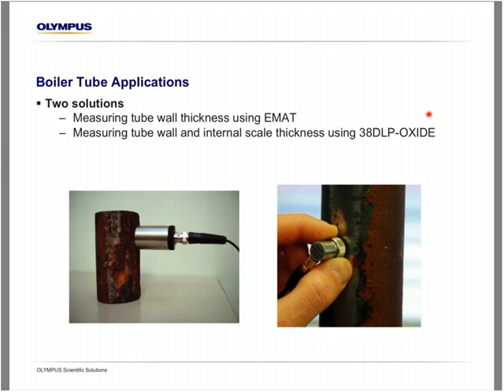So you can see that on the left here. This requires that external scale, and it's really designed to be an initial screening tool to determine if the boiler tube wall thickness is still within spec. Because if it's not, then there's really no sense in doing further inspection. It's better to just scrap the boiler. But if you do use the EMAT and you determine that the measurements are within spec, then they'll remove that external scale and do a more in-depth inspection using a single element delay line transducer and the internal oxide software.